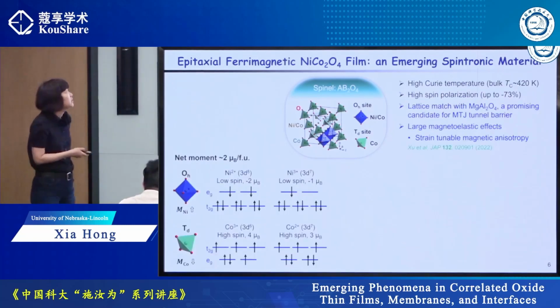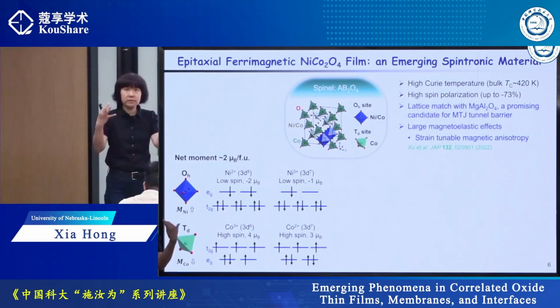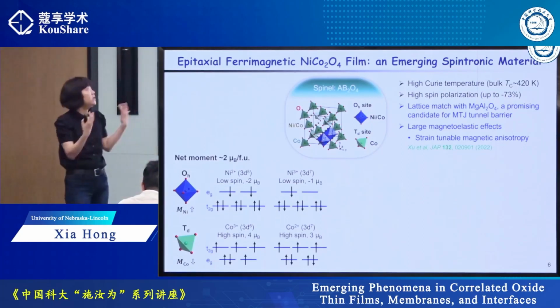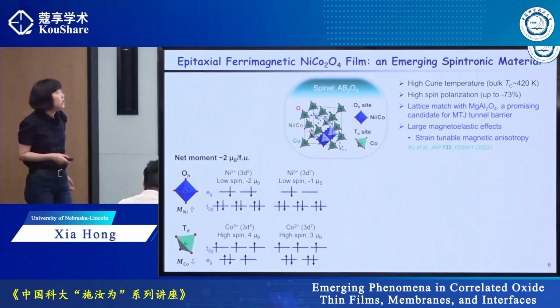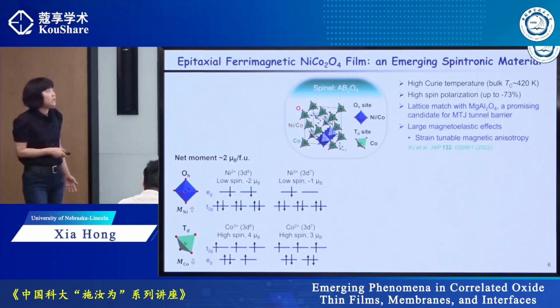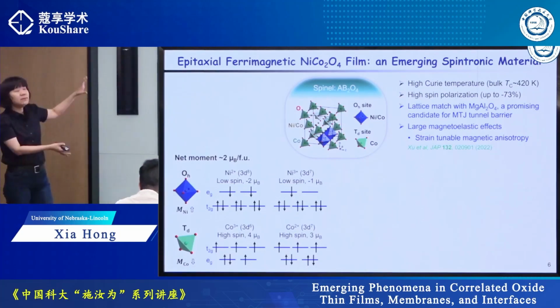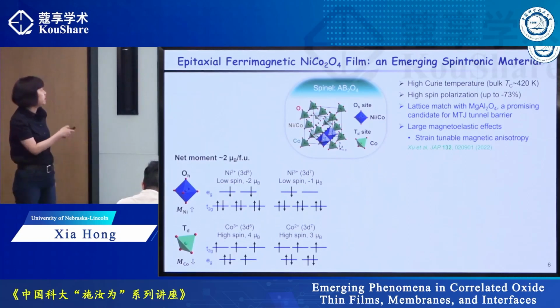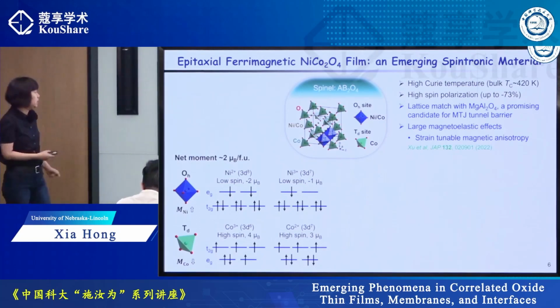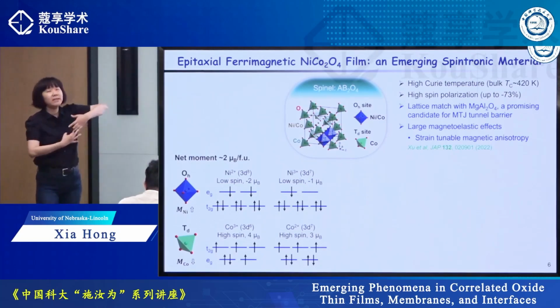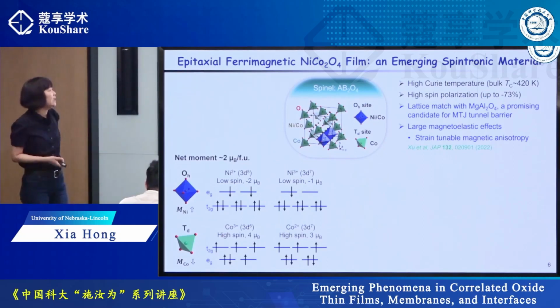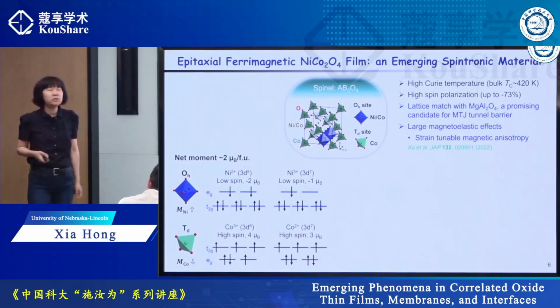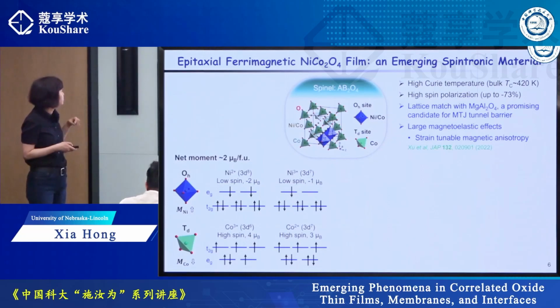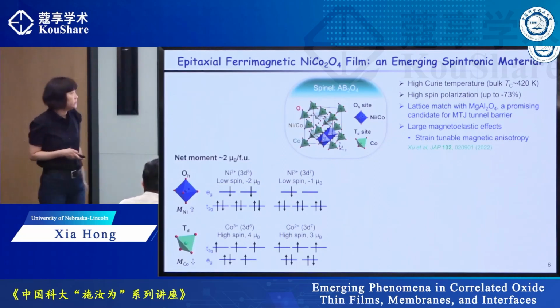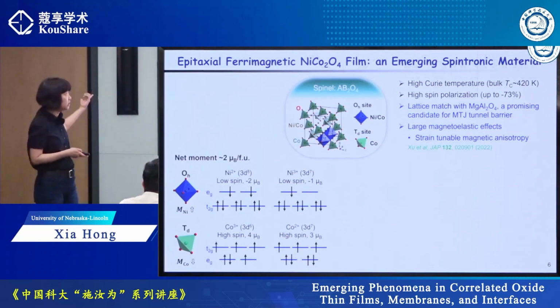On the other hand, this material actually has a very appealing magnetic property. First, it has a very high Curie temperature, above room temperature. It has very high spin polarization. And it's a ferrimagnetic material, meaning it has two sublattices. One is octahedral, one is tetrahedral, and the two sublattices' spins are anti-aligned, giving you a net moment of 2.4 Bohr magnetons per formula unit. So very high magnetization as well.